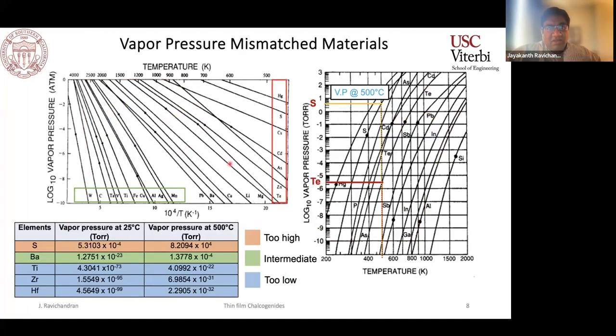The idea is the mismatch in the vapor pressure in these materials. So this is a plot of the vapor pressure of various elements that are of interest to us here. As you can pay attention to, something like sulfur, tellurium, and even selenium, for example, tend to have very, very high vapor pressures, even at very modest temperatures. Whereas the other materials, such as titanium and other transition metals that we routinely see here, tend to have very, very low vapor pressure, even at fairly high temperatures.